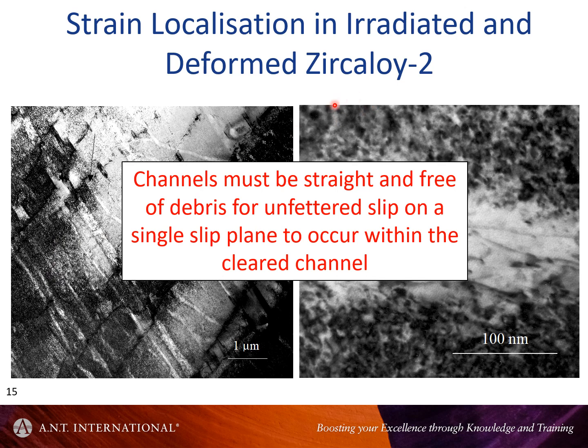So just to reiterate, the defects that were shown in that previous slide by Puyan, again this didn't work either, were nice and straight. I could analyze them as twins using diffraction. From my perspective, I wouldn't even care, I would be 90% certain that certain defects were twins just simply from the contrast and the shape.